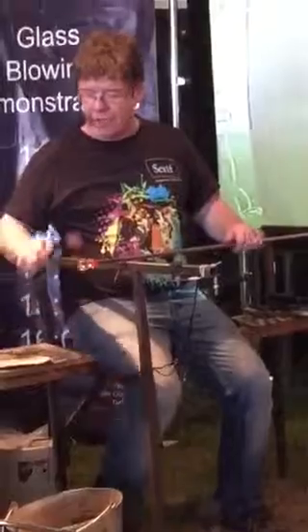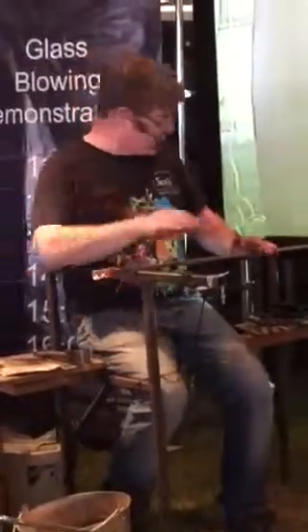And we're coming very close now to one of the most important ones of the lot. We're getting very close to the point where glass makers will actually say to each other that the glass has gone cold. Just about there now. And the reason it's so odd is because it doesn't mean it's gone cold, it actually means that the glass has gone hard. Okay, so all that movement that was in there is gone. It's not cold, it's actually incredibly hot.